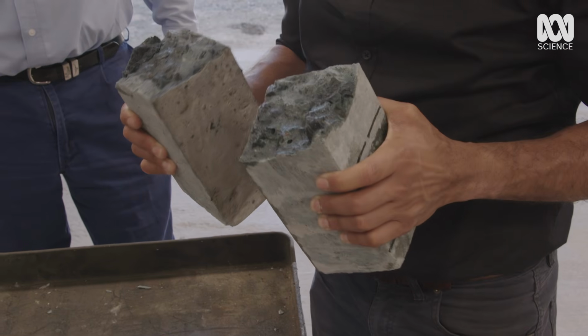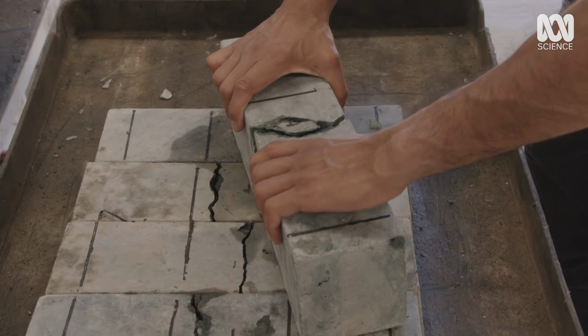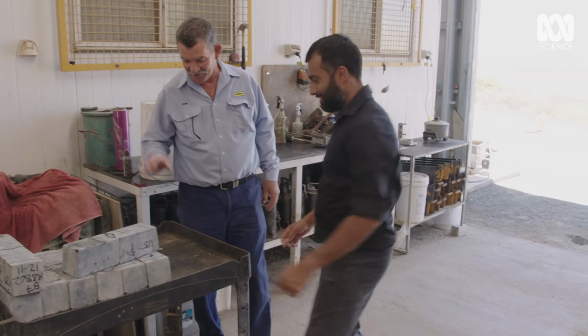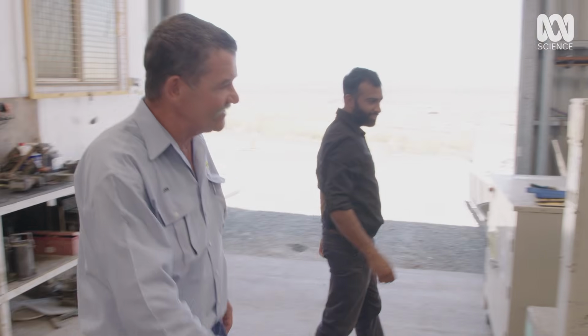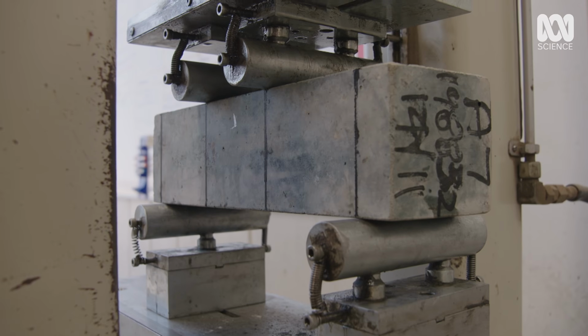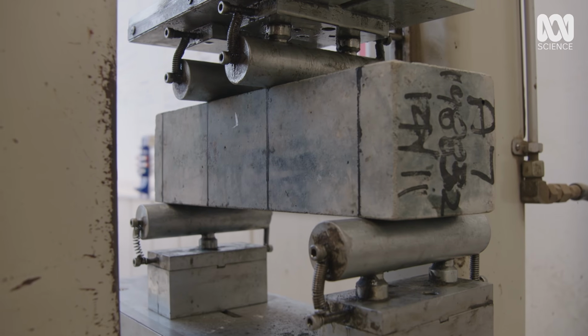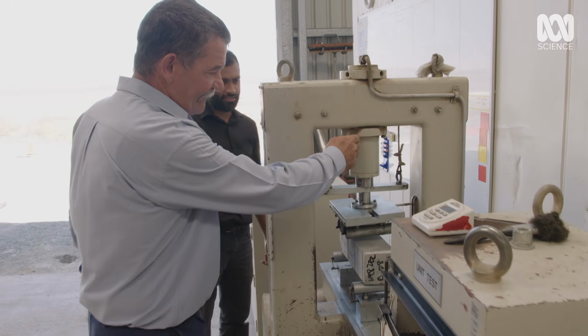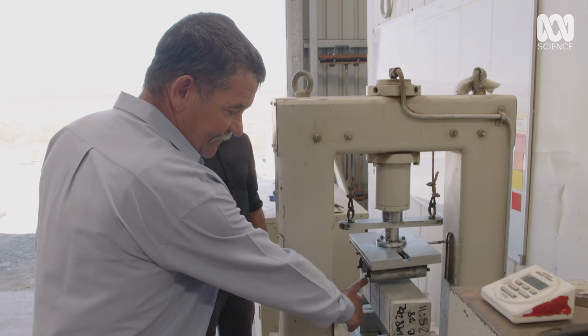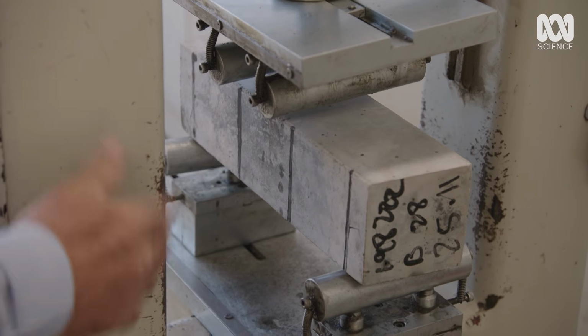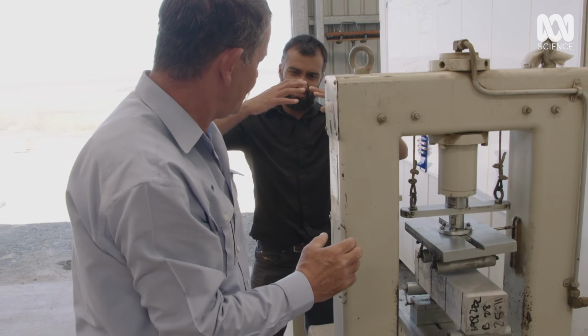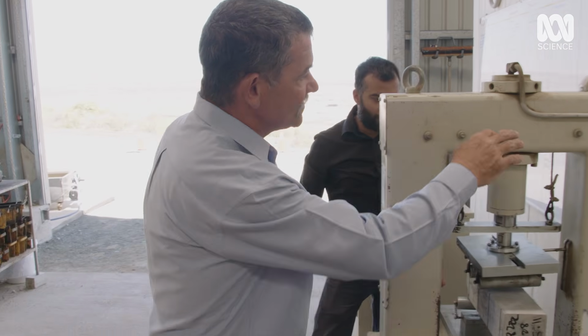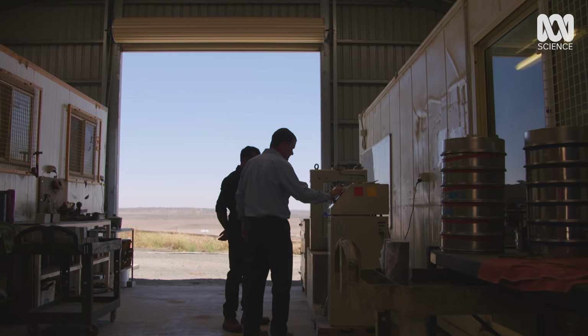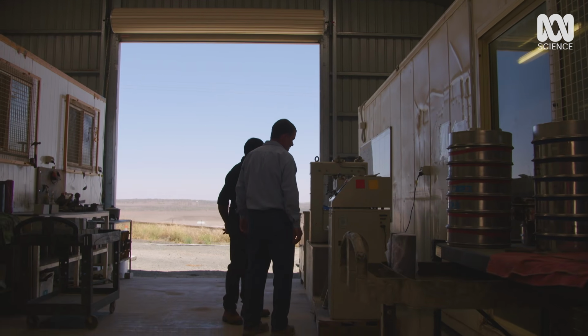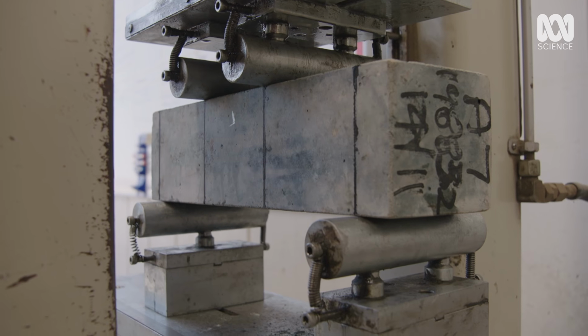We're about to put concrete poured 5 days ago to the test. All right, so these are tested in this machine over here. And to see if it can carry the weight of a large jet. We're actually measuring the amount of force it takes to fracture this sample down the middle. So you're measuring strength in this direction? In tensile, right? Concrete takes 28 days to set to its full strength, so this sample is still in its infancy.